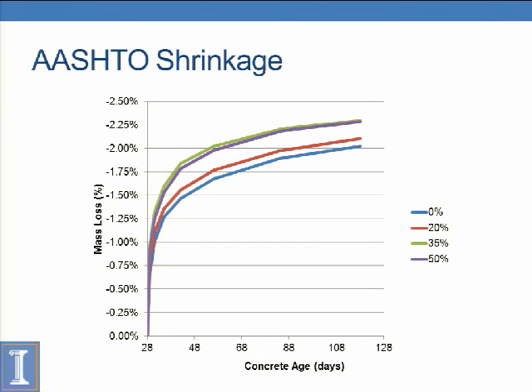Also with the shrinkage, you measure the mass loss. So every time you go to measure the shrinkage, you just weigh the beam and determine how much mass you're losing. And we found a slightly greater mass loss with the higher FRAP contents.